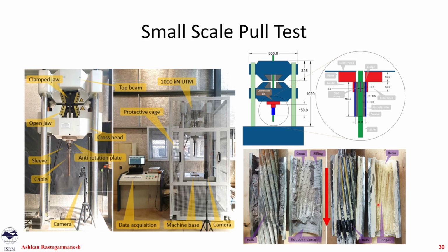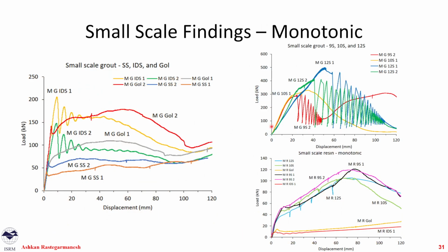For grout and resin, obviously our resin is more ductile, so we see less brittle damage, but in our grout, you can see the damage, and you see the direction of the pull here. The type of graphs that we got from our test are like this. Our post-peak oscillation was more attenuating, so it just tends to go down. And for our resins, we see a strain hardening behavior. Again, the details of them are inside all the papers that we published and the thesis itself.